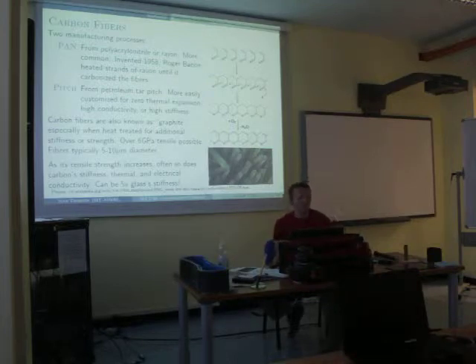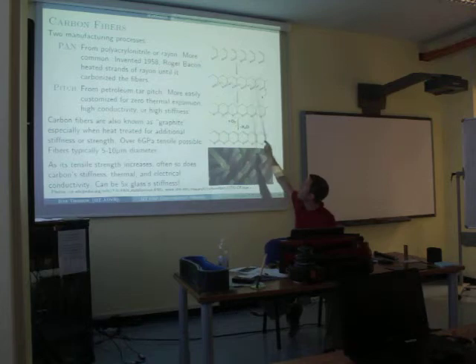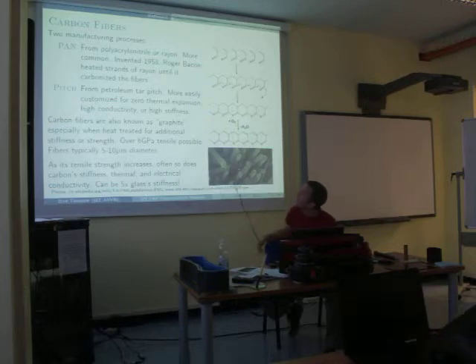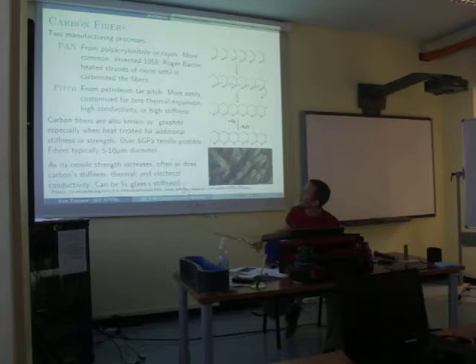The next most common material is probably carbon fiber, especially in the last 10 years. People are just loving carbon fiber because it's got that great black color, I think, more than anything. It looks cool. It comes from 2 different manufacturing processes. One is from polyacrylonitrile, or rayon, and it's a carbonization process. So they take some smaller molecules, heat them up, and then they start to form these long chains. I believe this is a synthetic molecule. It was invented in 1958, but it wasn't really commercially successful until about 10, 20 years later. The other way to make carbon fibers is from petroleum or tar pitch, also by carbonizing it, I believe. And you can sort of customize the carbon fiber a little more to have the material that you want.